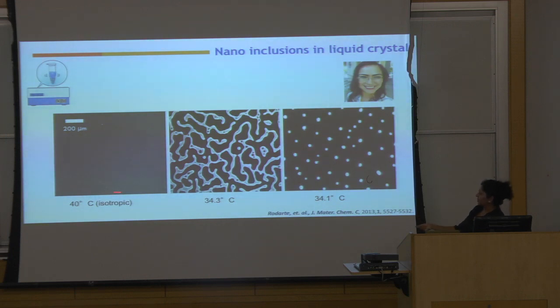At 40 degrees, the liquid crystal is isotropic, so it looks black. We are cooling down. The liquid crystal is starting to get organized, so it's expelling all the quantum dots into these defect parts till we come in. The phase has come in all the way, and all the quantum dots are packed together into defect regions. The rest of the liquid crystal is perfectly ordered. So we can have the liquid crystal bring about some sort of self-assembly of the quantum dots when we started out with a completely dispersed system.